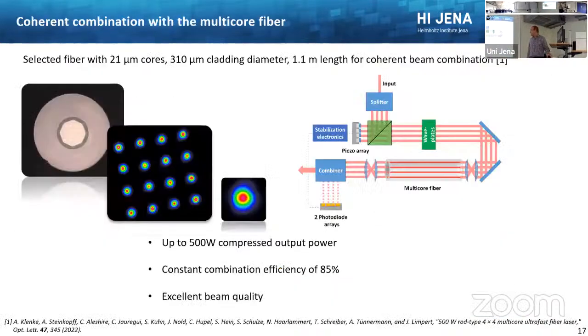And in the first step, we produced such a fiber. So this is also a rod type fiber. It's not a flexible fiber, so about 1 meter length. You can see a microscope picture on the left side with all these different 16 cores in it, and this ring for the pump guiding. And you can also see you get 16 very nice output beams out of this fiber. And we managed, with all the other components, to build up a complete laser system operating up to 500 watts of average power. It has also quite nice combination efficiency and also excellent output beam quality, as you can see also in the sketch.